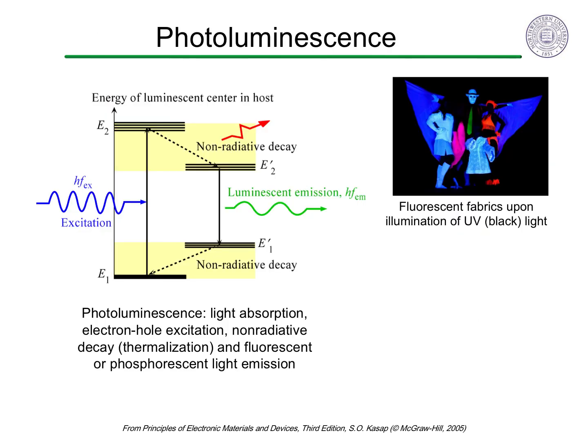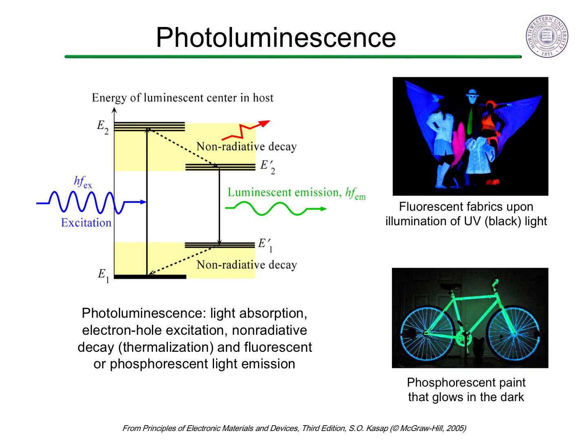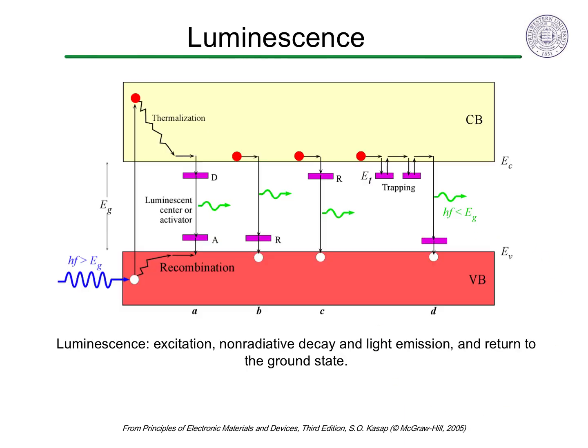After an electron is excited, it eventually relaxes back to the ground state. Fluorescence is the immediate re-emission of light, usually of similar or lower energy. Both the electron and hole can reduce their energy or thermalize by giving some energy to lattice vibrations or phonons. If the electron or hole flips spin or wanders off to where it is more difficult to relax back, the process can take much longer, producing long-lived phosphorescent light.